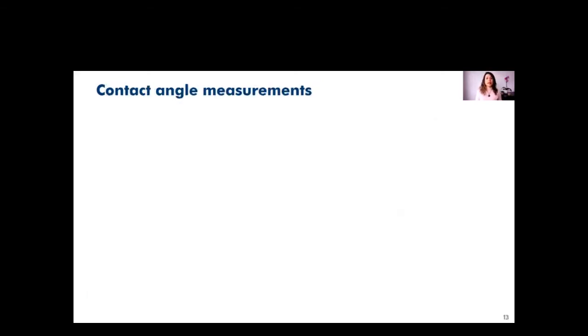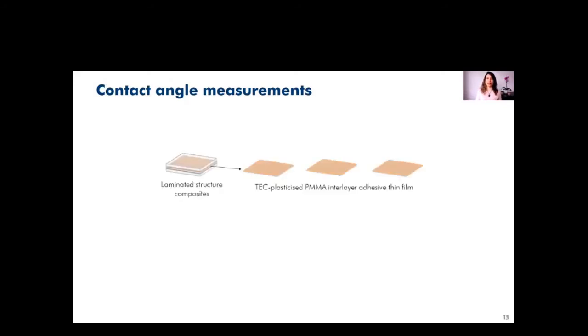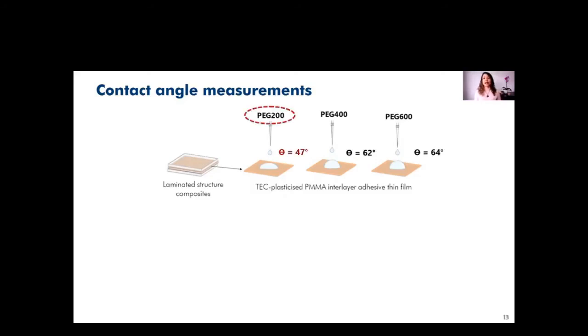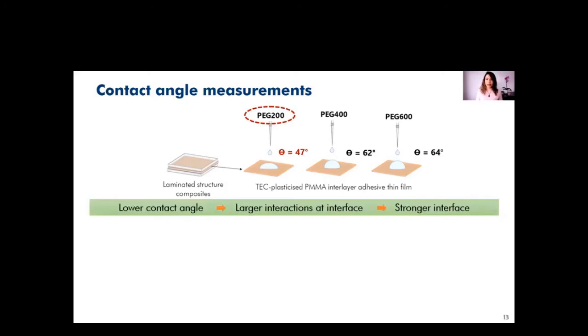To understand this, the contact angle between the interlayer in a thin film form and the liquid PEGs was measured. It was found that the contact angle of PEG 200 was much lower than the contact angle of PEG 400 and 600 with this interlayer adhesive, and there is not a big difference between PEG 400 and 600. A lower contact angle means there will be larger interactions at the interface, and that can lead to a stronger interface.